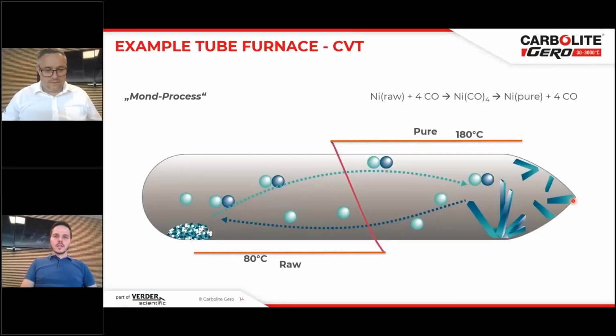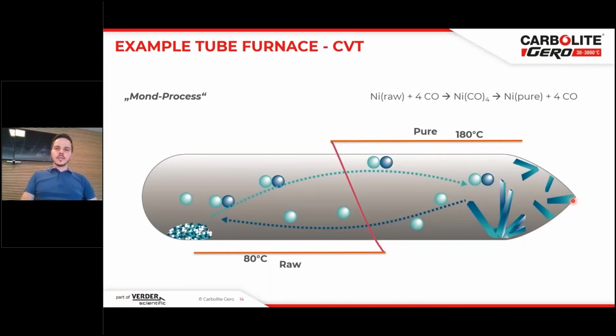Yeah, in a lab scale, the last process, the Mond process, is achieved via a so-called chemical vapor transport reaction. On one side of an ampule, you have the raw nickel, and on the other side, you have the pure nickel, which is transported with a gas. In this case, it is carbon monoxide. It is a molecule which connects and binds to the nickel, and then it brings the nickel into the gas phase, and in the hot zone it decomposes and crystals of nickel are grown. Well, this is just a very small lab process.